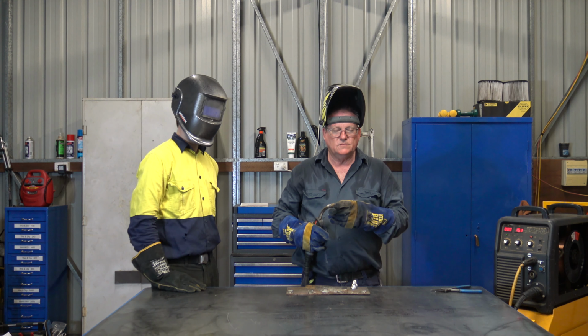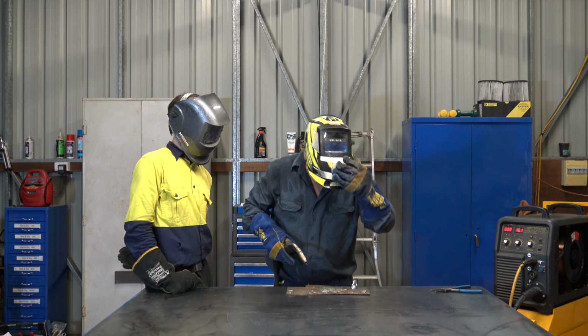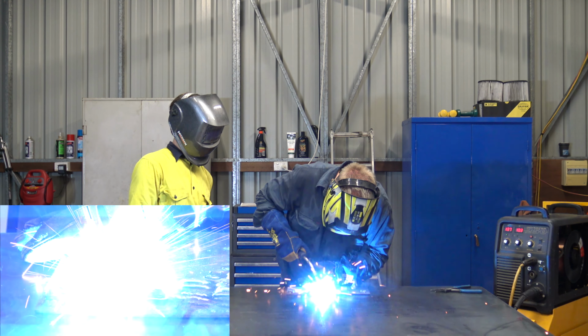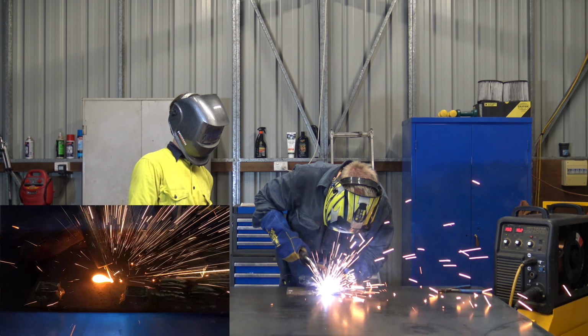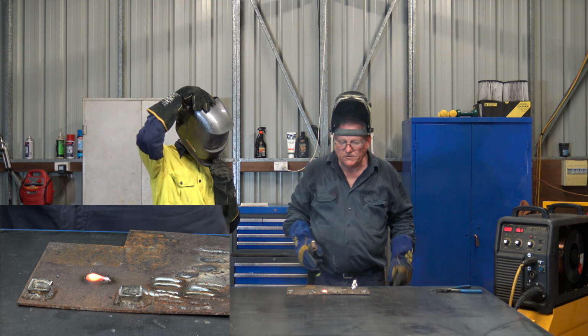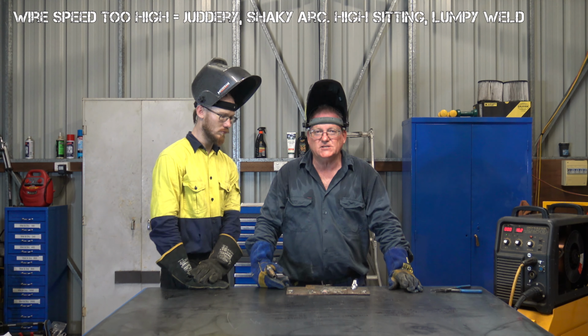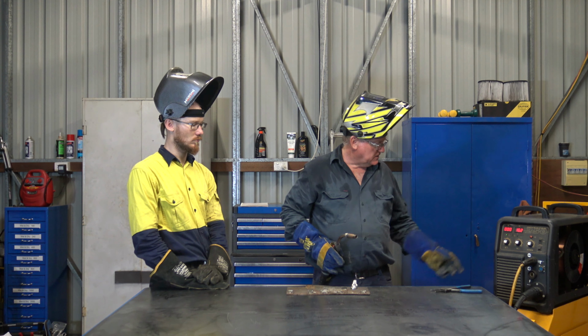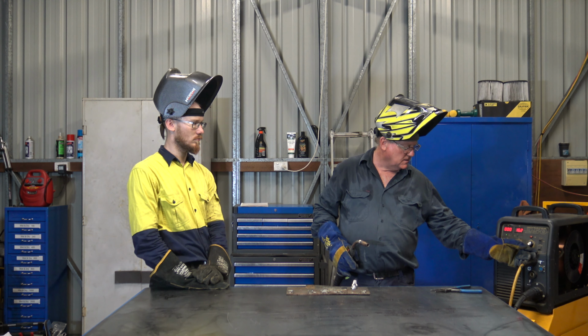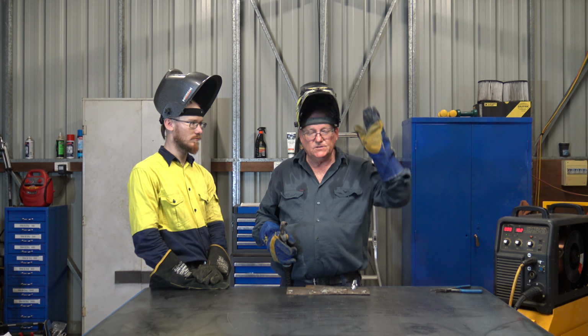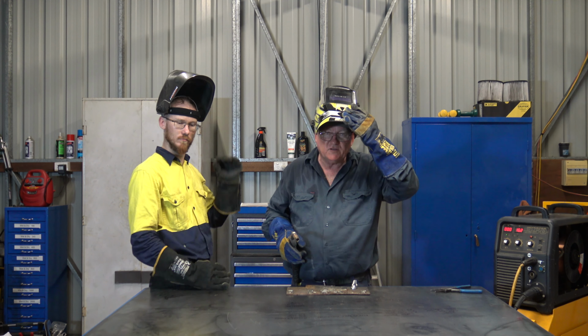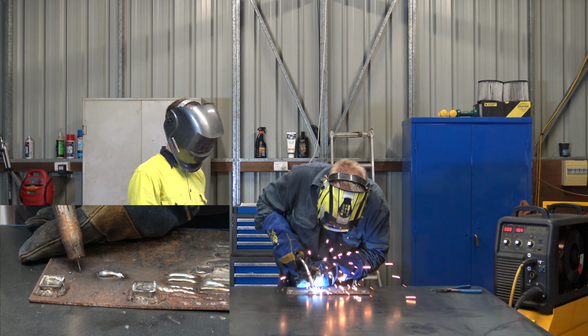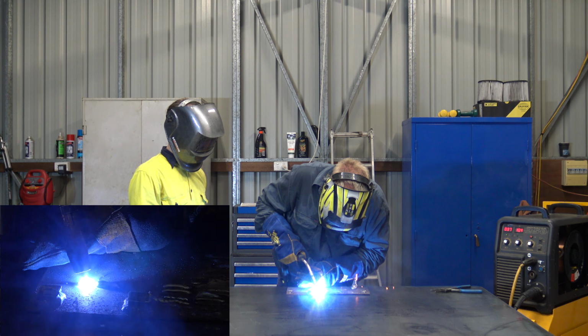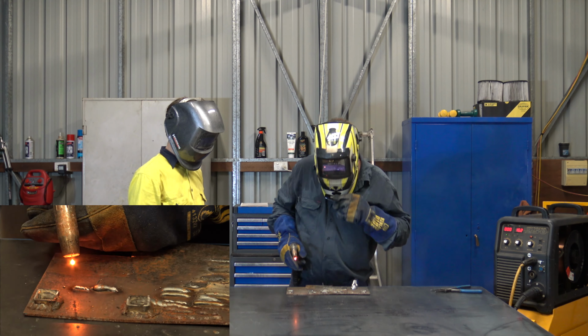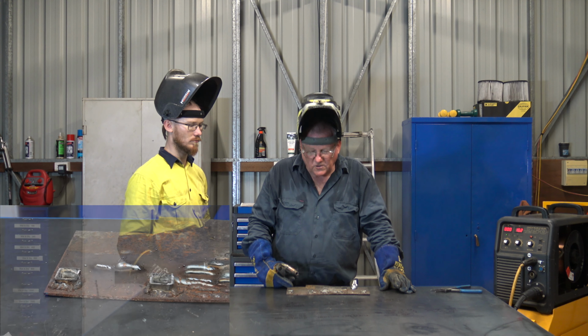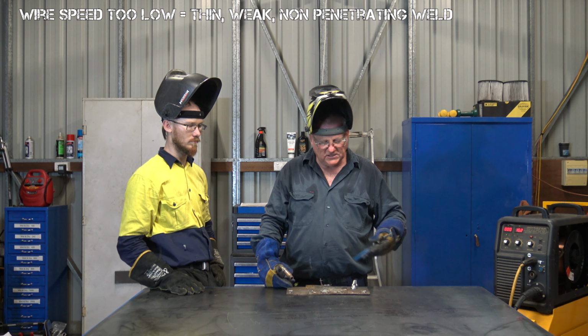So we'll start off with the wire speed too high and just see what that sounds like and looks like. That didn't sound well at all, and we've got a very high lumpy weld that's sitting on top. It's not actually wet into the parent metal. So that's way too high. Let's turn the wire speed way down and see what not enough wire for the voltage looks like. So that's a very thin looking weld that's sitting on top and not at all a successful weld.